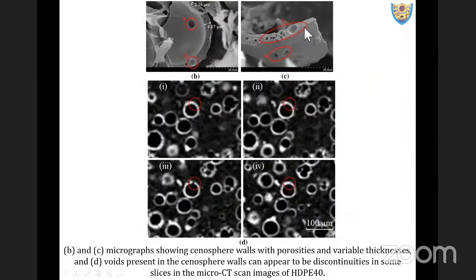Because these fly ash cenospheres are naturally burnt ones, they have a lot of surface defects on the surface, within the wall also. This is the broken cenosphere. If you can see this, the wall thickness is variable and even the wall is porous. So when you do the micro CT of this, though the microballoon is intact, it seems to be broken because of these inbuilt wall thickness porosities. So we need to interpret the micro CTs carefully.